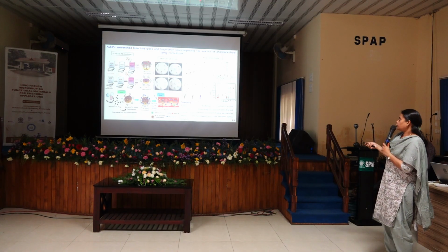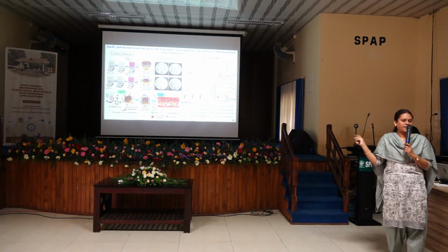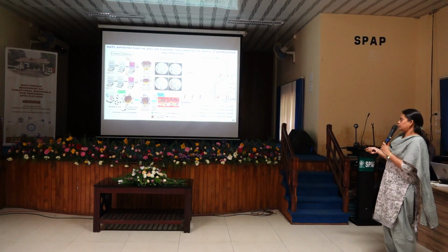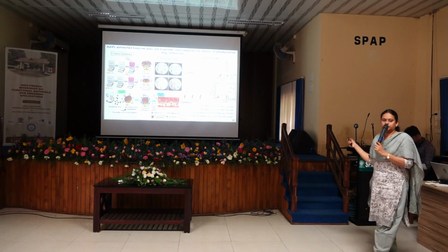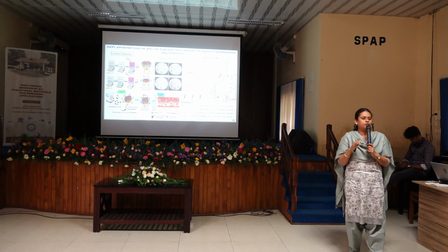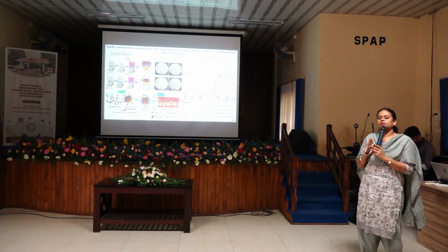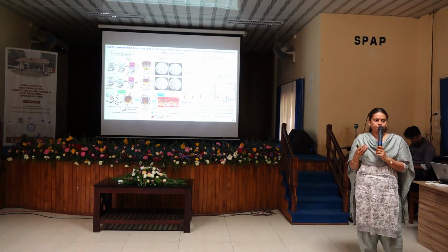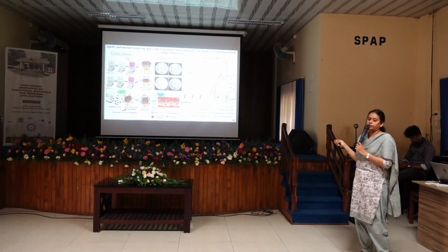In that, the zero order model has shown a correlation coefficient of 0.9 R square, which is well suited for the bioglass gold chitosan composites. Other methods are not suited because of the dissolution factor of bioglass and gold nanoparticles, and also the non-diffusive nature of chitosan. So the materials stick with the zero order kinetics.